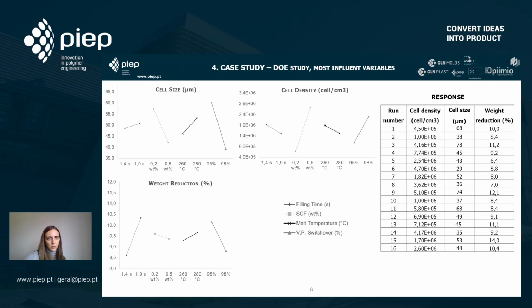In the case of cell density, we want to have higher cell density. So again, we can see that the 0.5% of gas is the best result for this part, and again 98% of the filled cavity promotes also higher density for the part. But when analyzing weight reduction, we can see that the influent parameters change a bit. So what we can analyze is that the filling time is one of the most influent parameters, along with the VP switchover. It's also another very important parameter.